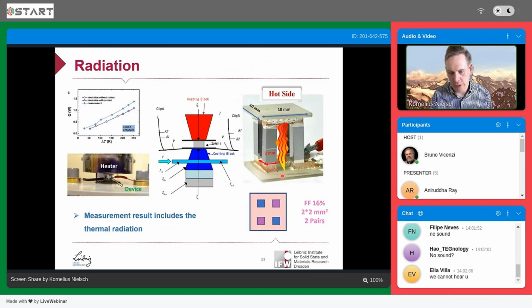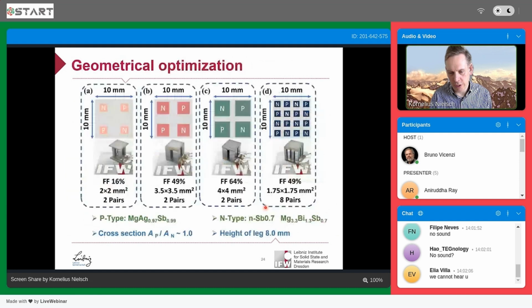The first design had just a filling fraction of 16%. So 16% of the area of the device was covered, when we looked on top, by the thermoelectric material. And so we worked on different modules with enhanced filling fraction, starting from 16% going to 49%, and then the densest device was about 64%. By this strategy, we could further improve the overall device performance by using this higher density.